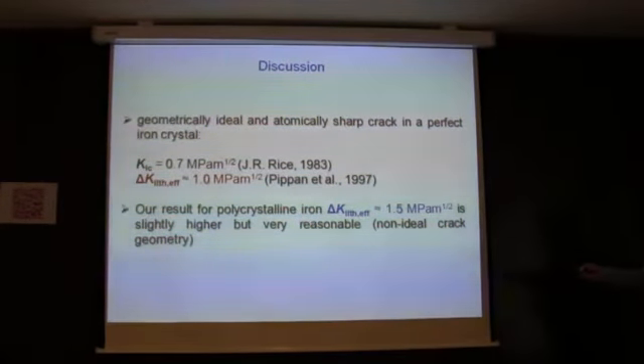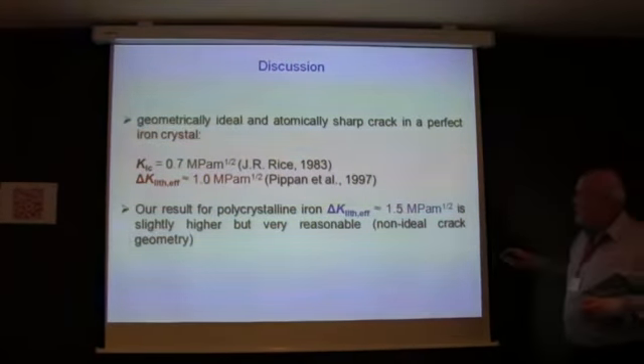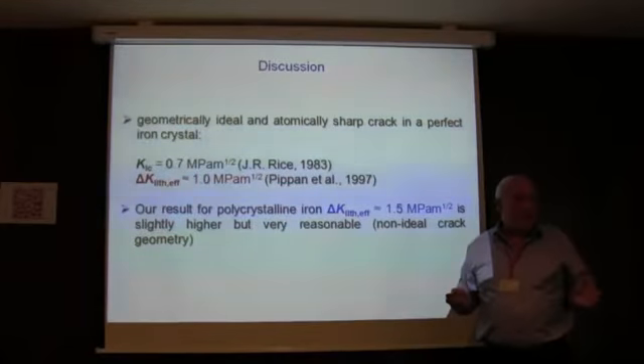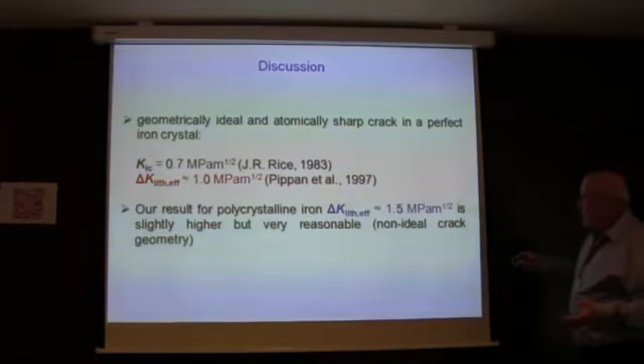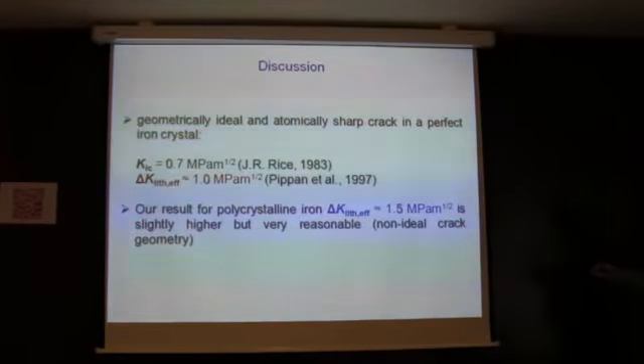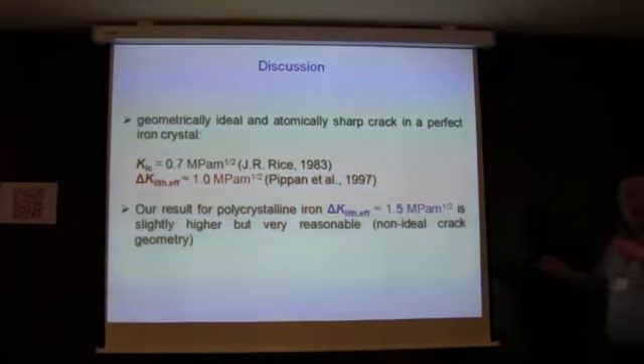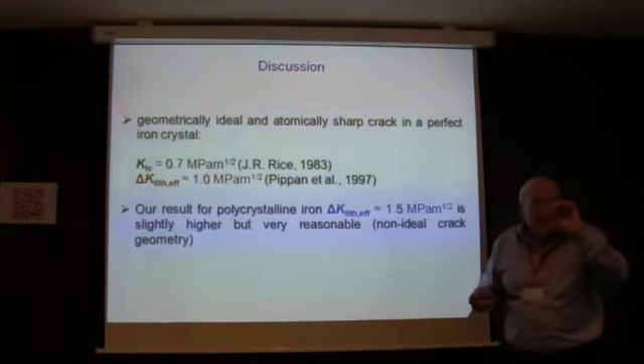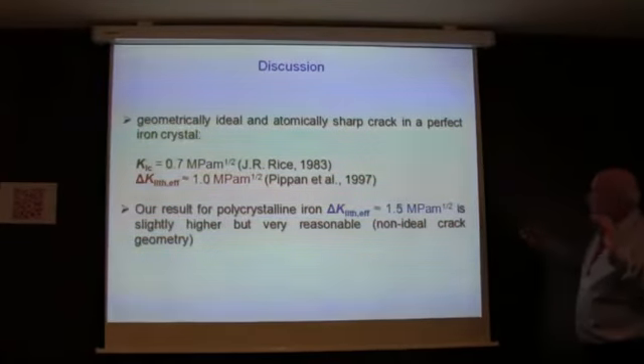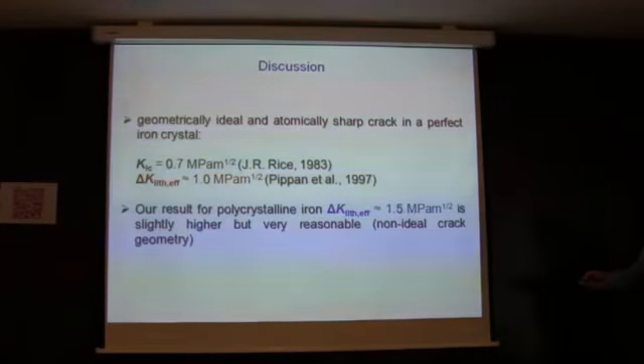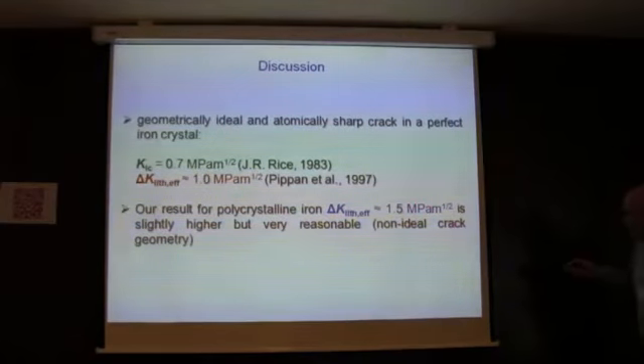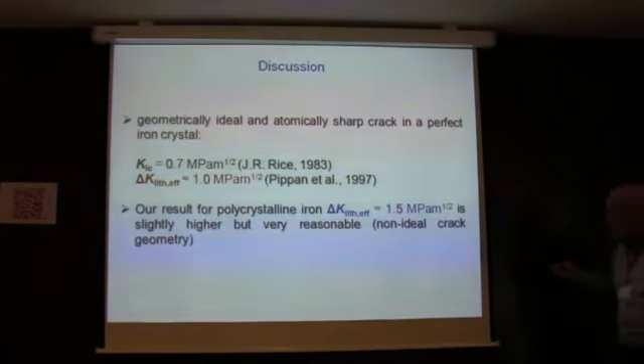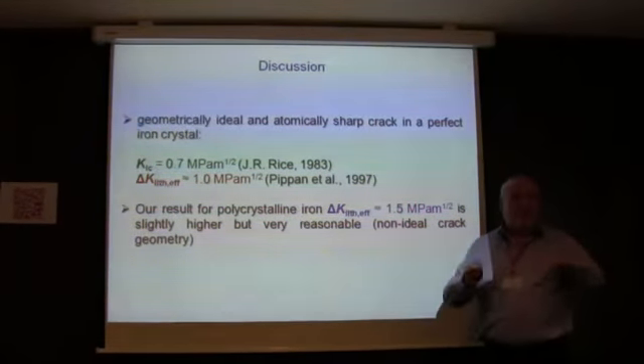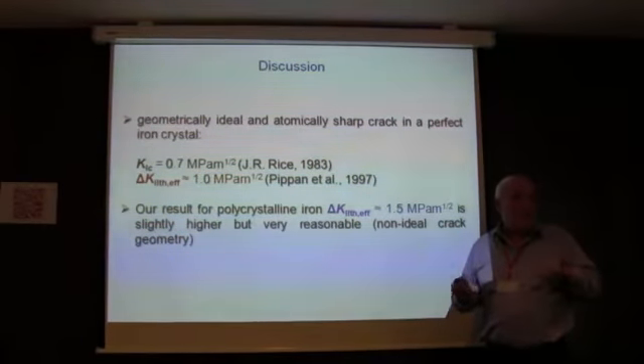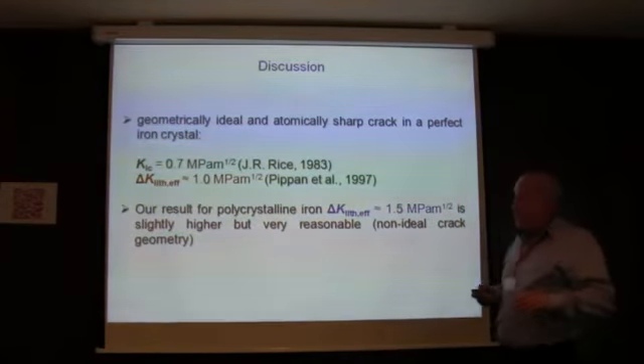And our result for polycrystalline iron, as you could see, is 1.5 megapascal. So the difference is not so far away from that. And it is understandable because you do not have ideal conditions. Some plasticity at the crack, it's not ideally sharp, and other factors. So some higher values could be expected. So we believe that we really reach the effective values of the thresholds.